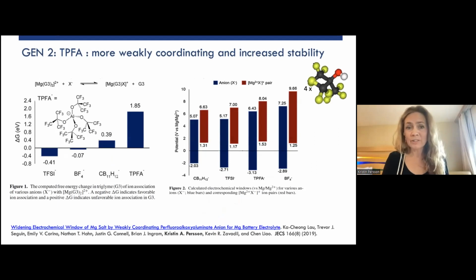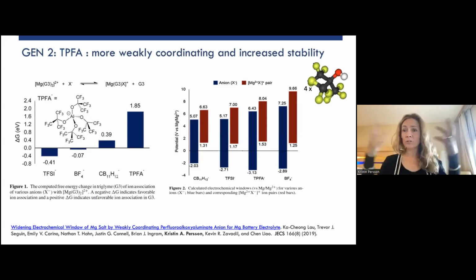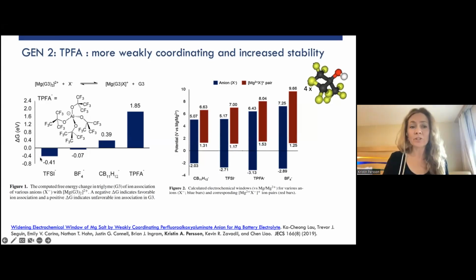And as computational evidence of this, you can see here that we calculated the Gibbs free energy of the coordinated version, so magnesium coordinated in a contact ion pair versus solvent separated. TFSI, which is again not known for being a highly coordinating anion, actually likes to coordinate with magnesium, but TPFA is highly resistant to it. So this is truly something that will have a very, very small presence of contact ion pairs in the solution. And indeed, it's also predicted to increase the electrochemical window of your solution, of your battery. So in that sense, we were hoping that this would be a good electrolyte for magnesium applications.